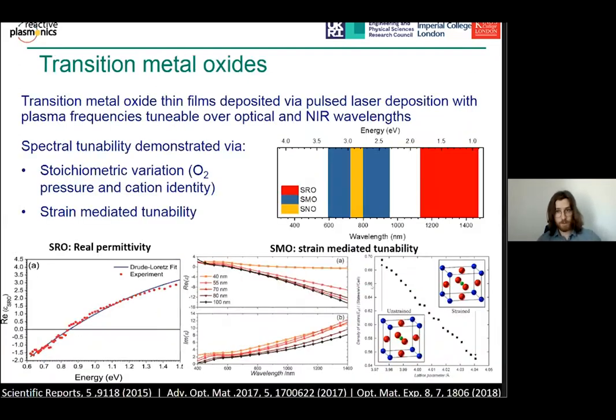So this is all theoretical, so we wanted to confirm the materials that we've selected experimentally. So we developed our deposition methods. For example, we looked at transition metal oxides deposited by pulsed laser deposition. We show that these are tunable over optical and near-infrared wavelengths.